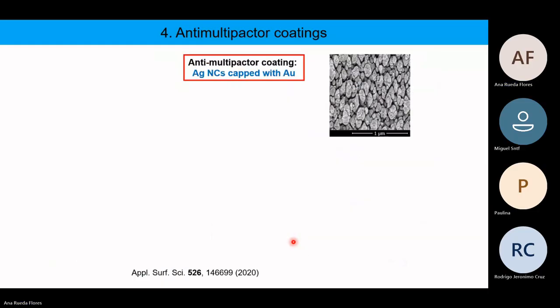So here are the best coatings that we have produced up to now. They are made of silver nanocolumns, but that we have capped with gold. We have capped with gold to prevent oxidation, because silver oxidizes in ambient conditions. This is something that our grandmothers knew. They were always cleaning the cutlery to remove the oxide from the knives and forks.